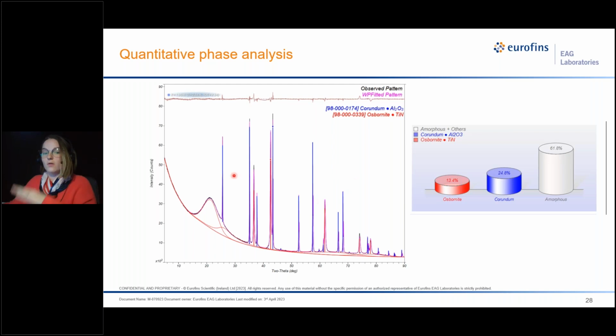And if you know that all of your amorphous material in your quantitative phase analysis is the same amorphous material and you know the density, you can do quantitative phase analysis with amorphous material. If you have more than 1 type of amorphous material, it's not going to give you any kind of realistic answer in terms of percent weight and quantity.